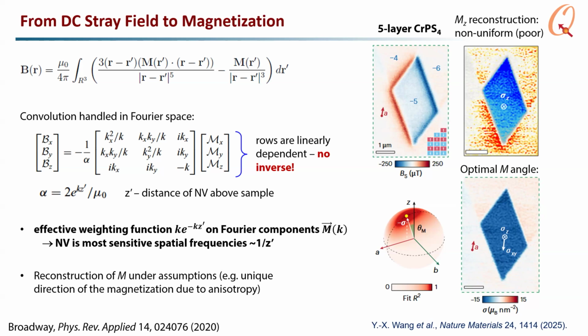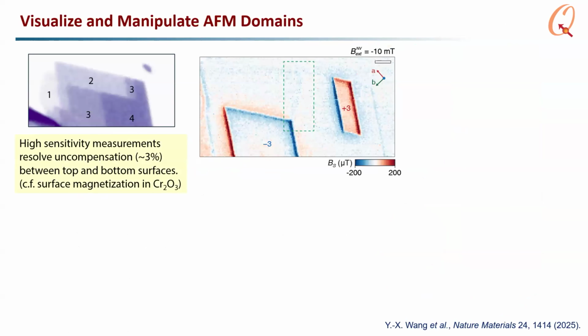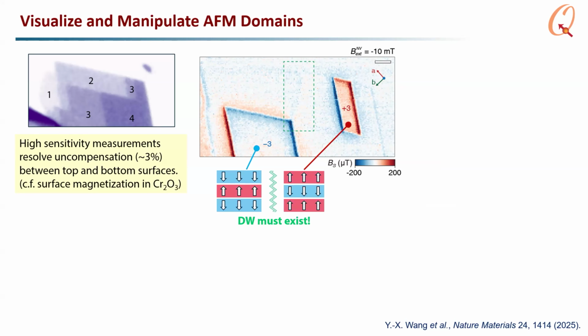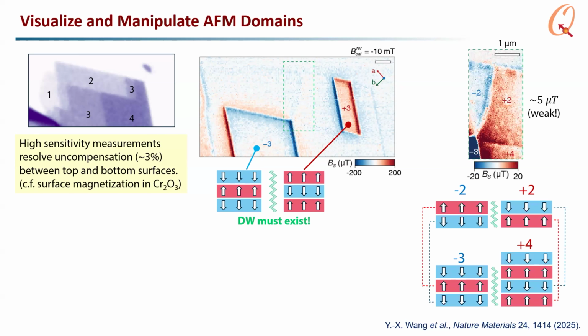But you may notice that there's a little bit of reconstructed magnetization sort of outside the flake, and that's not noise. It's actually coming from the even layer regions. So here is a sample that has between 1 to 4 layers, and we see that the 3-layer regions are in opposite states: down, up, down for the blue, and then up, up, down, up for the red. But this sample is connected, so it means there's a domain wall somewhere. So can we see that domain wall? And actually, the domain wall cuts right across the bilayer.